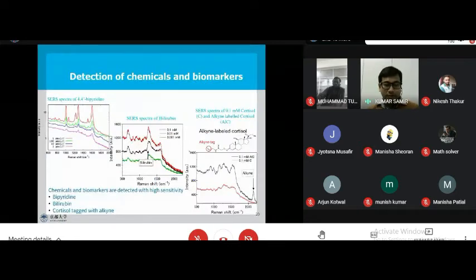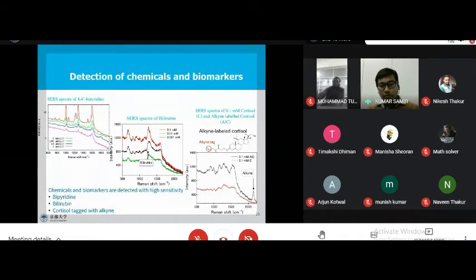So using this, we detected different biomarkers and chemicals. This is the standard Raman probe, and you can see we can detect up to 1 micromole per liter. And also, we were able to successfully detect bilirubin, which is the biomarker for jaundice. And we also detected cortisol, which is released during stress. So this is also a biomarker.